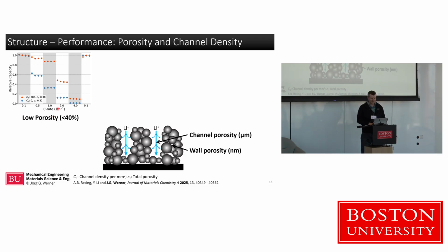And we find now, again, on the x-axis here is for different C rates, when we charge it very slow over 10 hours, we get full capacity. And then if we go to something like 2C, which is a 30-minute charge, for one of them, we essentially only can put 10% of the capacity in. For the other one, we can put 50% in. And that other one is the one that has the channels with overall similar porosity. So the channels really seem to do something for these fairly thick electrodes.